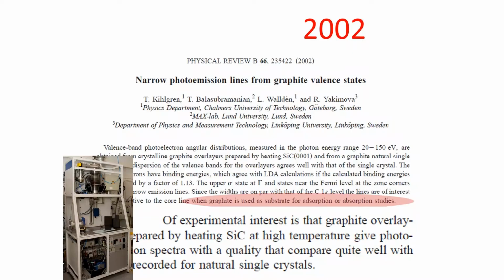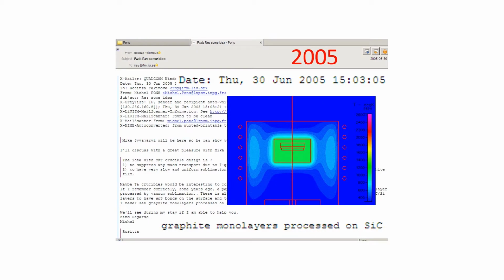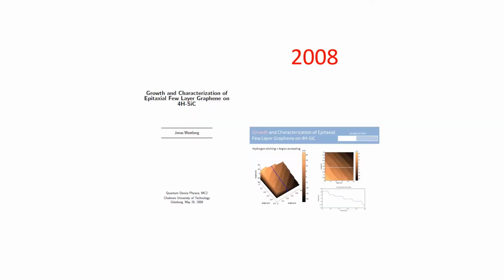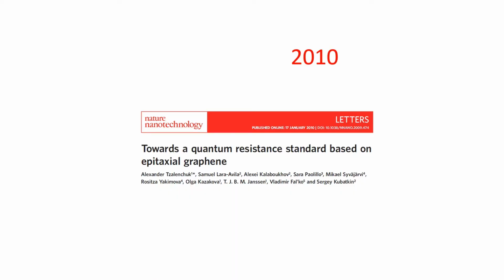And this we started to explore for thin graphitic layers 20 years ago. There was a researcher who was interested in this graphitization of the silicon carbide, which was not good for the growth. But when we did it intentionally, we could have thin graphitic layers, and they had very high quality. Over the years, we studied these thick graphitic layers and made them thinner. And in 2005, we had one layer of carbon on silicon carbide. So that was the graphene. But we were not fully aware what this was good for. But as a grower, we were very interested in that. Then we continued the studies and had a diploma thesis in 2008 and so on. Then in 2010, a very nice result of using this material was demonstrated. Together with other researchers, they presented results towards a quantum resistance standard using epitaxial graphene.